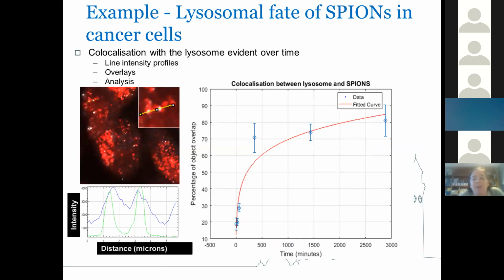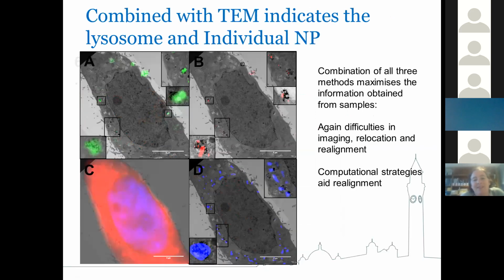So by looking at the co-localization over time, we can start to see whether there's increasing accumulation, or if we have a fixed pulse of particles, and then we track the cells. So we expose only for an hour or so, and then we track the cells over the next 24 hours. We can look then at the degradation of the particles, or, for example, the dilution effect due to cell division and so on. So really understand the fate of the particles.